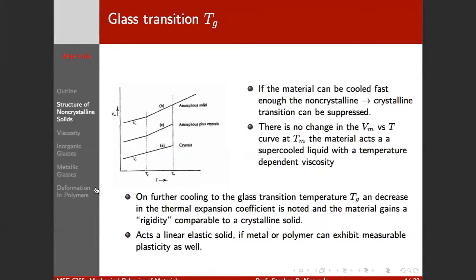change in the volume versus temperature. So we see a change in the thermal expansion coefficient once we reach the glass transition temperature, because it's not easy for vibrational short-range diffusional transformations to occur locally to accommodate